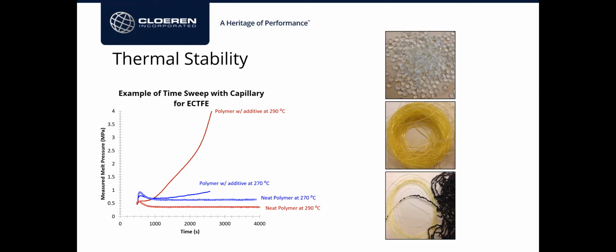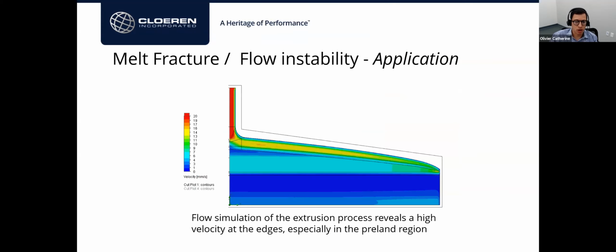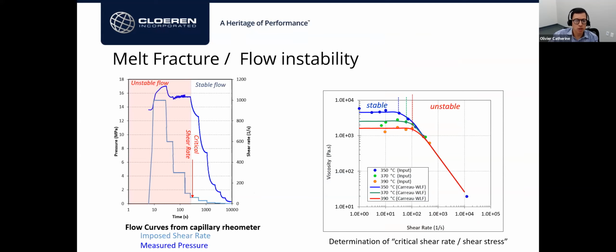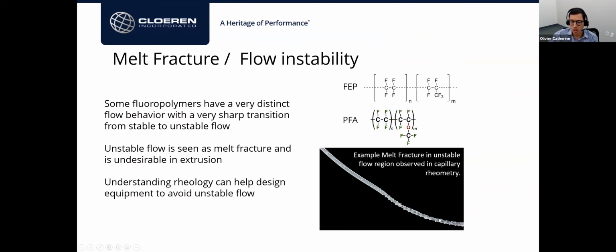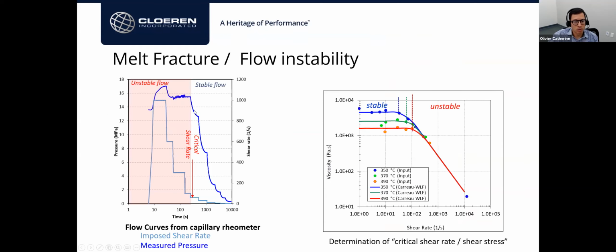Next, how do you identify the critical shear rate for a specific polymer? Well, I thought I explained that. Basically, looking at the pressure graphs as a function of time, you could see the oscillation and characterize unstable flow. And then at some point the flow becomes stable, and this actually matches the extrudate. So you see that type of melt fracture going on, and then at some point the flow becomes stable and the extrudate becomes smooth. The transition between the two is your critical shear rate or shear stress, and that's one method to do that. Okay, next, how can a melt fracture be anticipated?